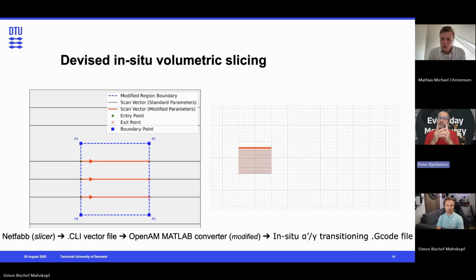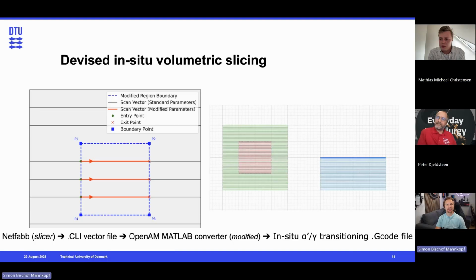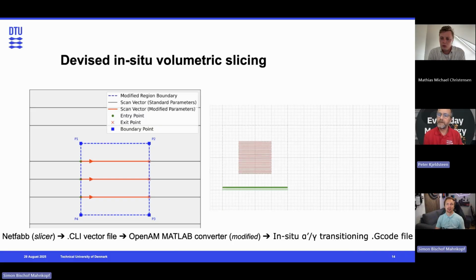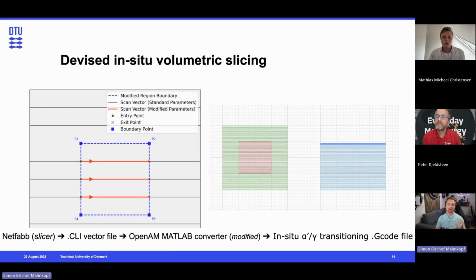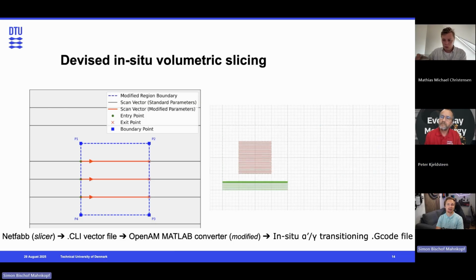But you are still within the process window that you started, the green arrow. You're not going into lack of fusion or into pinhole creation. Yeah, exactly. That's the difficult part of this, because we are using the energy, the thermal gradient, to try and create the difference of martensite and austenite. So we use a higher energy to get the martensitic transformation. And when we do that, we obviously have the process window we have to stay within. And that's been one of the limiting factors for how low can you go in martensitic content and how high can you go in martensitic content. You have to try and find that process window you can stay within. And that's where you have to look at other processes like post-process treatment to get the higher martensite content.